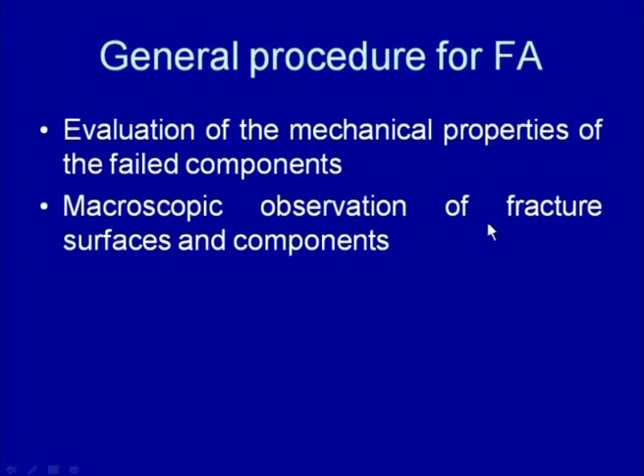Then the macroscopic observations. The next step can be the macroscopic observation on the fracture surface and the component. Macroscopic observation on the fracture surface of the component is performed using low magnification lenses, and the stereo microscope magnification will be below 50x. It can range from 1 to 50x, and when it is performed, it gives us